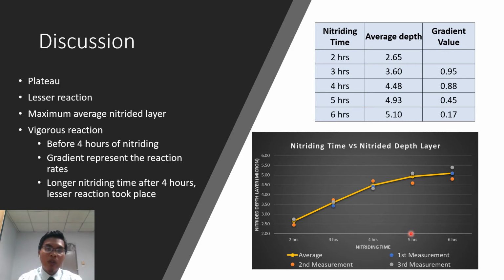So before 4 hours of nitriding time, the reaction between the magnesium and the nitrogen becomes vigorous. So the gradient can also represent the reaction rate between the magnesium and nitrogen. Based on the trend, we can easily say that the longer the nitriding time, the deeper the nitrided depth formation. However, after 4 to 5 hours of nitriding time, the reaction between the magnesium and nitrogen becomes lesser and lesser. So the plateau is expected to be around 7 to 10 hours of nitriding time. After that, there is no reaction taking place between the magnesium and nitrogen.